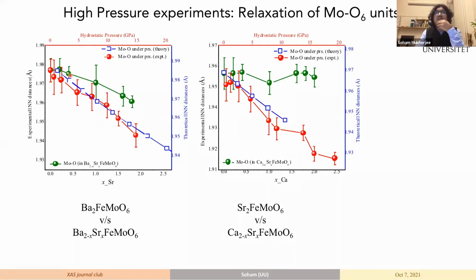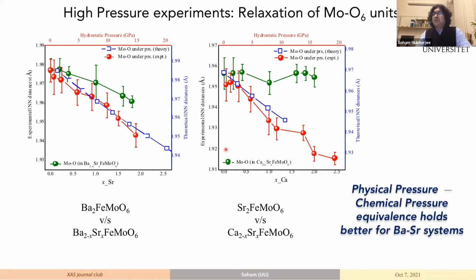So we see that there is a stronger scaling of the molybdenum oxygen distances under pressure. But when it comes to the doped system, we see that when we dope in calcium, the system really doesn't scale with high pressure as you would expect from the difference between physical and chemical pressure. So we see that in both cases, the equivalence between hydrostatic pressure and chemical pressure holds better for the barium strontium system, where the bond angles are close to 180 degrees, which preserves our previous hypothesis that bond angle should remain invariant when you are trying to do a chemical size substitution.